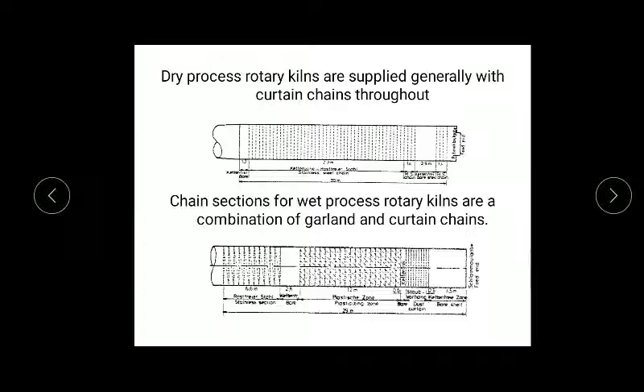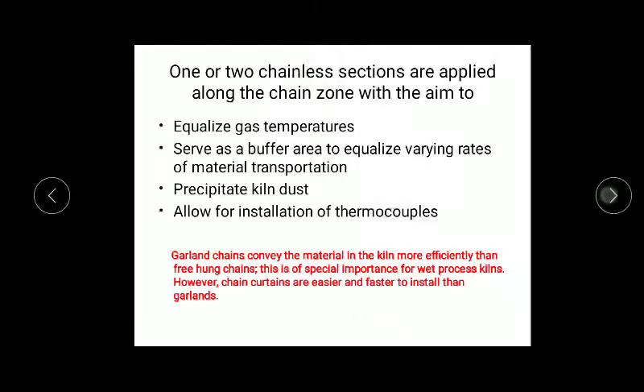Dry process rotary kilns are generally supplied with curtain chain throughout. In the dry process, the chains are throughout the rotary kiln. And the chain section for wet process rotary kilns is a combination of garland and curtain chain both. You can see these are the garlands and these are the curtain system. One or two chainless sections are applied along the chain zone with the aim to equalize gas temperature, serve as a buffer area to equalize varying rates of material transport, precipitate kiln dust, and allow for installation of thermocouples.